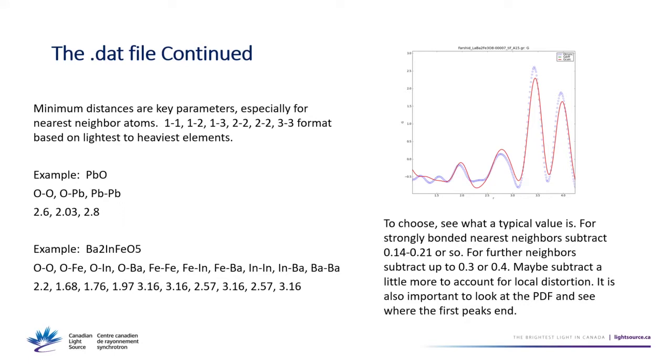If you make it a little further down, it might start putting distances in here, and you get some weird differential. So I would do it as a combination of figuring out what a typical distance is and what a reasonable thermal motion around that is, along with looking at where you have minimums in the PDF. Generally for the shortest distances, these parameters are very important. For atoms that are further apart from each other, it's not so important. That will generally take care of itself.